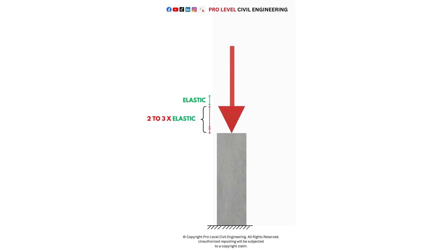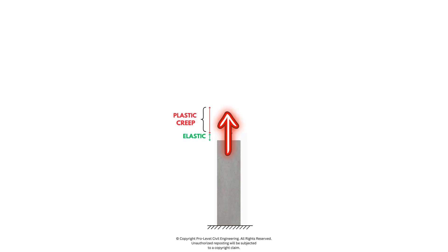The final deformation from creep can be two to three times the initial deformation. If the long-term load is removed, the member will recover most of its elastic strain and a small portion of its creep strain.